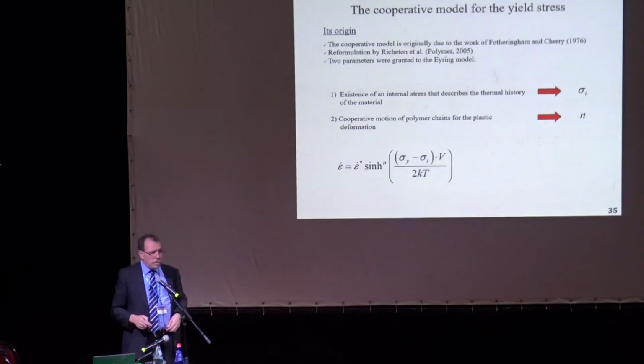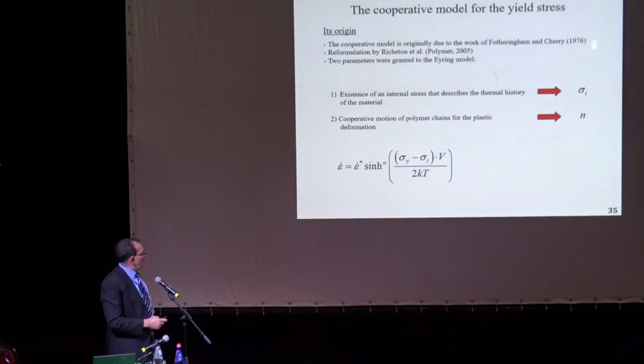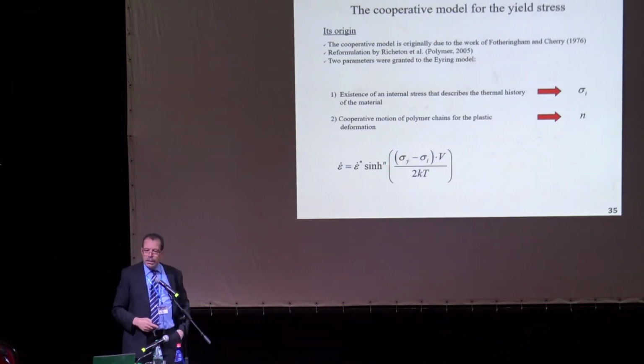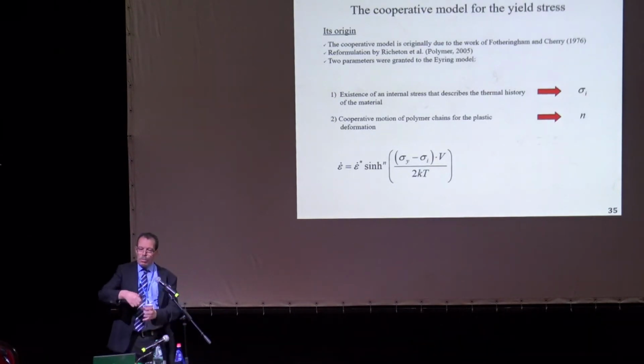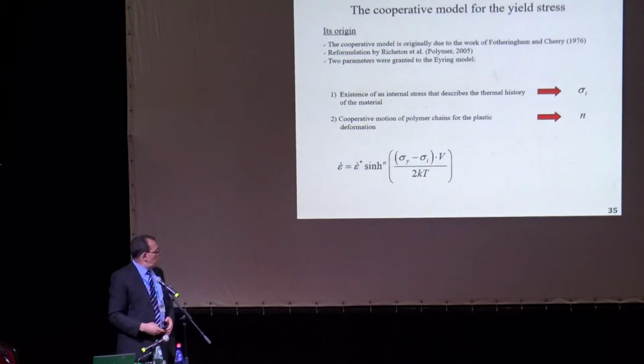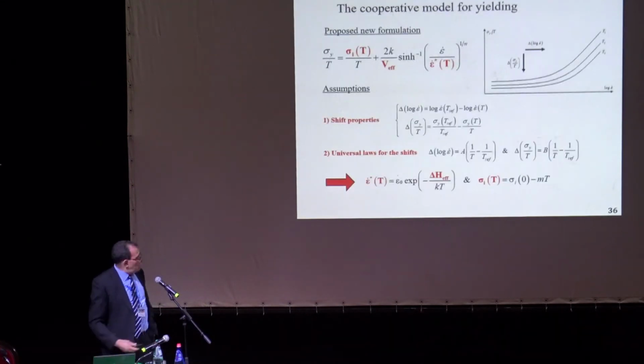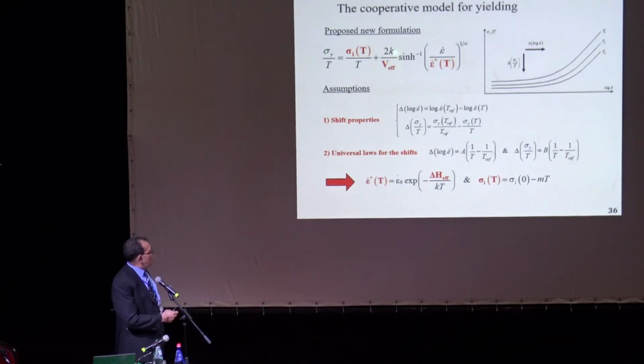That's what we developed. What we call here the cooperative model. And in fact, we found an old work by these two authors, and we reformulated what they have done, by taking the Eyring model. The Eyring model has no n here. This term is 1. Okay, we introduced this n here, which is linked to the number of segments in the polymer that are cooperatively in motion during plasticity. Okay, and then we introduced an internal stress as well. Okay, that pre-exists in the material. Now, by doing that, this is what we get. This is the yield stress normalized to temperature, is the internal stress plus this term here, which depends on the activation volume and depends on this characteristic strain rate.